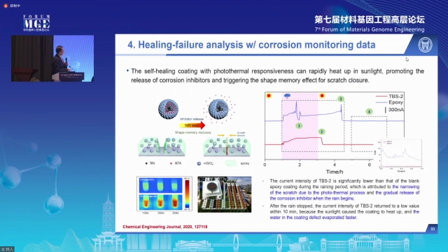And we can see that during the rainfall period, the magnitude of corrosion current is much smaller than the conventional coating and more stable because, first of all, the sun will help with the surface scratch closure on the self-healing coating, and also during the rain, the inhibitors will diffuse and also suppress the corrosion on the surface. But what's more interesting was that after the rain stopped, we can see the current on the sensor with the self-healing coating quickly drops to a very low level, but it takes hours longer for the current on the conventional coating to decrease.